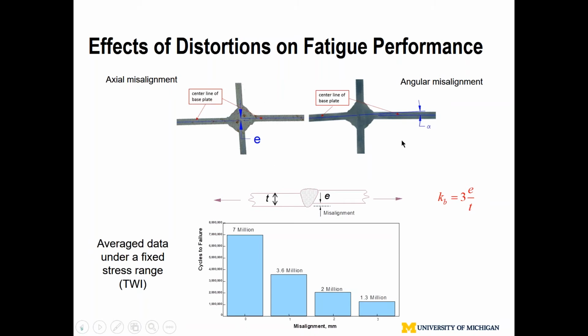But for this component, because of the poor design, the design engineer did not consider how this gets built. That means the design was not for distortion control. This component cannot be fixed, cannot be corrected, because the application is very sensitive to heat. Even if you apply heat, or apply local bending, the structure is inherently unstable, again because of the lack of structural rigidity, the lack of diagonals. In shipbuilding we call them transverse frames. It doesn't have that. So this type of design simply cannot be built to the accuracy intended for this particular application.